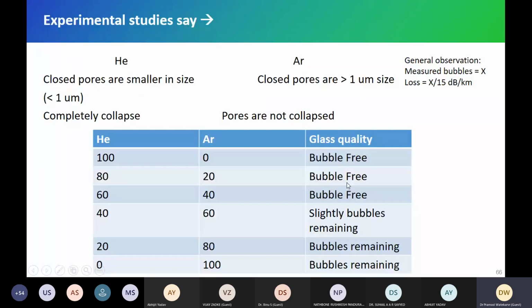I think I should not discuss this helium argon, but just generally what we use: we put helium and argon gas to remove those pores. 100% helium gives completely bubble-free glass, but helium is very expensive. So we add some argon there. If you add argon, there is a lot of possibility that bubbles can be formed. So the optimum ratio is very important.